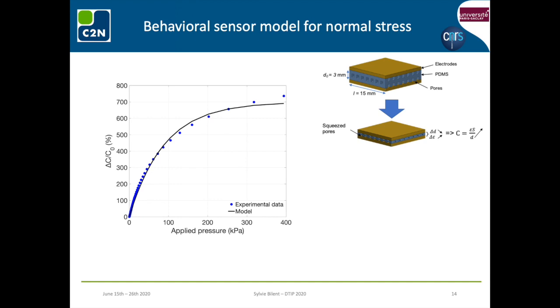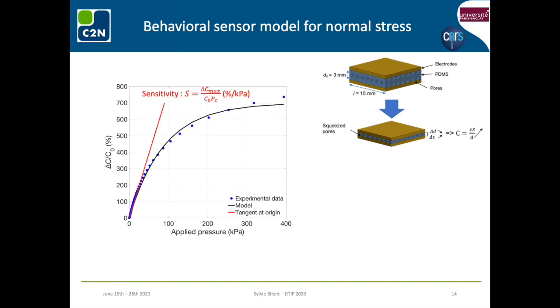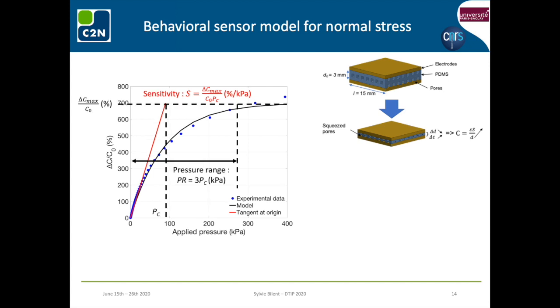Here is a typical electromechanical pressure sensor's response expressed in terms of capacitance change in percent versus applied load expressed in kilopascal. In order to extract sensor's performance from this type of nonlinear curve, we define the sensor sensitivity as being the slope of the tangent at the origin of the sensor response. The sensitivity is denoted S and is expressed in percent per kilopascal. Moreover, we define the pressure range of the sensors as being 3 times the value of the characteristic pressure denoted Pc. Pc is defined by the intersection of the slope at the origin of the curve and the maximum value of the variation of capacitance. The pressure range is denoted PR and is expressed in kilopascal.